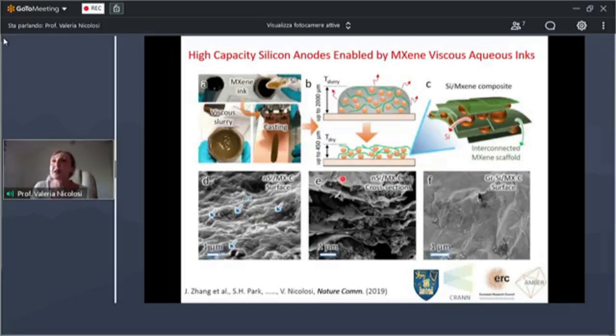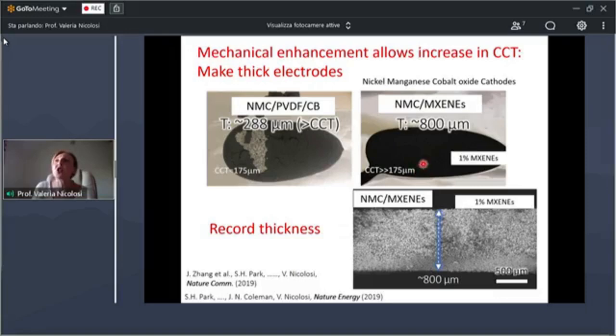What we realized was that the MXene sheets were organizing and self-assembling themselves into 2D blankets that were surrounding the silicon nanoparticles. This was really nice because not only did they provide electrical conductivity to the electrode, but they also completely mitigated the volumetric expansion and compression of the silicon throughout cycles. By doing that, we managed to achieve very high record thicknesses. And of course, the thicker the electrode you can make, the higher the capacity that you can achieve.